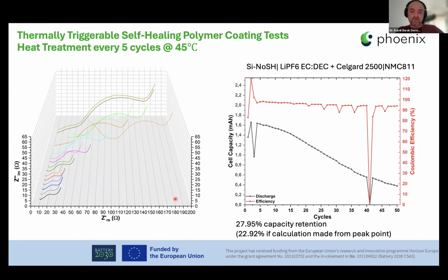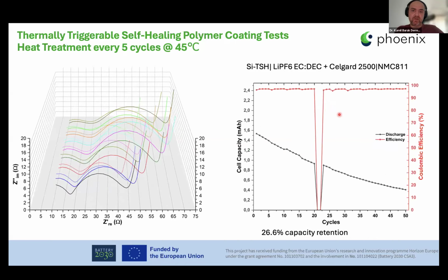electrochemical results. The results show that there is a continuous decrease in capacity, as expected from the silicon cells, of course, and you will see from the Coulombic efficiency drop the exact positions where we applied the heat treatment. But in that case, we don't see any visible improvement from self-healing effects in the electrochemical performance.